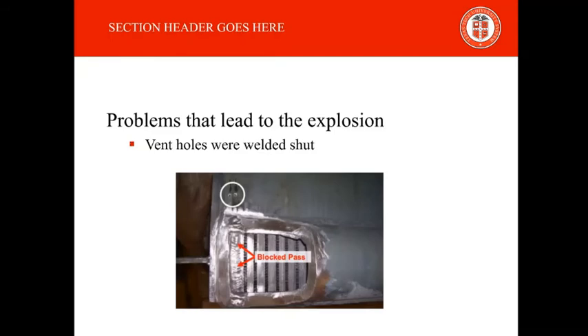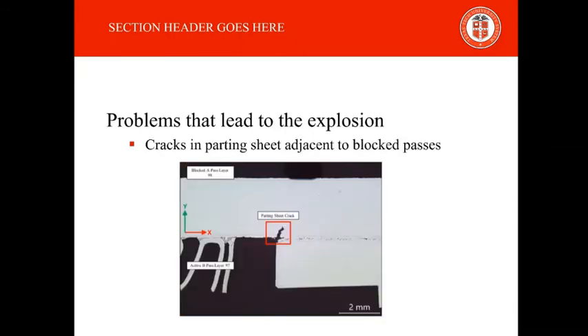The blocked ventilation holes inside the blocked layers would not have caused the problem by themselves. For a catastrophic rupture to occur, hydrocarbons must have a way to enter these layers and create the pressure inside them. The parting sheet that separates one of the blocked layers, layer 98, and one of the non-blocked layers showed evidence of thermal fatigue cracks and can be seen in the figure below.